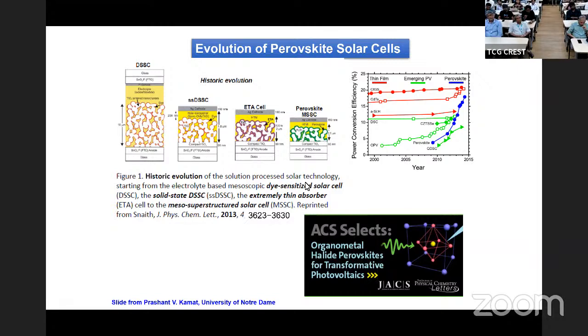Everything adds to the cost as well as the energy that you have to put in to fabricate those devices. This material, you can produce in a very energy cheap manner. Basically, solution processing at 100 degrees, 120 degrees, 150 degrees, you can make these in various solvents, and you can coat this on anything that you want very easily with very little cost. Not only that, these are extraordinary absorbers of photons, such that a very thin layer of this material can absorb all the photons that are coming in, and therefore you can make very thin cells, and that is shown over here.